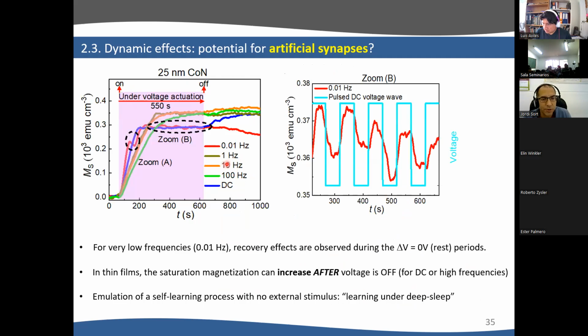The first one I want to show is that if we go very slowly, the signal is lower. And we want to understand this. And actually we measured slowly here, this zoom B is this area, this region here. And there is a correlation between when we apply the voltage and we stop.